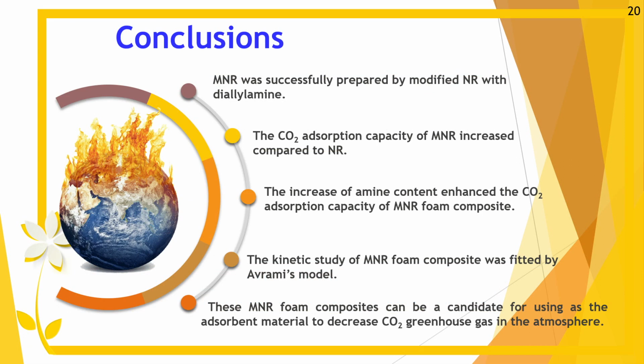According to this result, we can conclude that modified natural rubber was successfully prepared by modifying natural rubber with diallylamine. The carbon dioxide absorption capacity of the modified natural rubber increased compared to the natural rubber. The increase of amine content enhanced the carbon dioxide absorption capacity of the modified natural rubber foam composite. And the kinetic study of the modified natural rubber foam composite was fit by using the Avrami model. Accordingly, this modified natural rubber foam composite can be a candidate for use as an absorbent material to decrease the carbon dioxide greenhouse gases in the atmosphere.